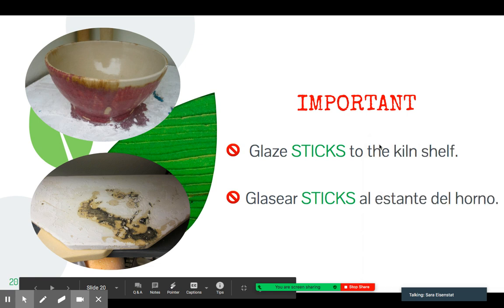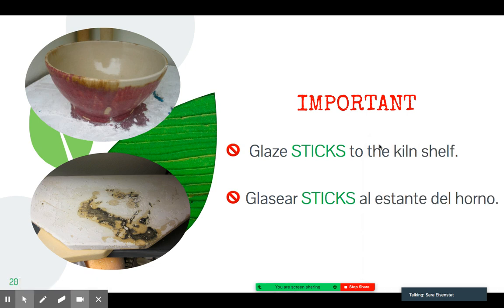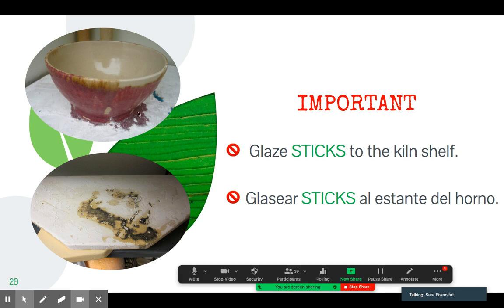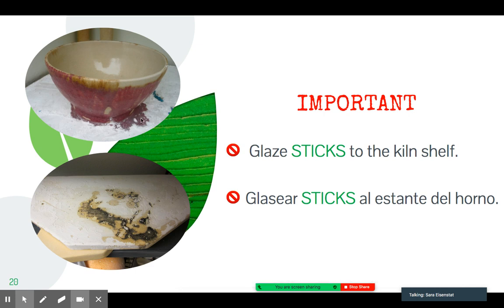Okay, this is what it looks like when we don't wipe the glaze off the bottom. You don't need to write this down, but it's important that you see what happens. So that silica starts to melt, and the flux, even though it controls the temperature, there's nothing that we can do to avoid it sticking if we leave glaze on the bottom. That glass will fuse to my kiln shelf, and then I'll take the chisel and I'll have to break off your piece.